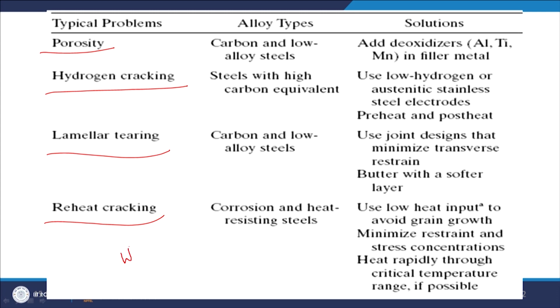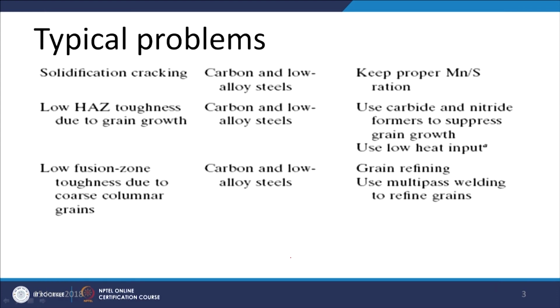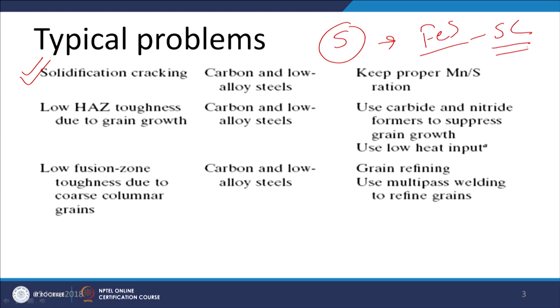In this case, basically the weld joint develops some undesirable phases, and when such a joint is again subjected to higher temperature, either during stress relieving or during service, the high temperature exposure leads to the development of cracks, and that in turn leads to reduced weldability of the metal. Another aspect which governs the weldability of steel is solidification cracking. Most steels have sulfur which during welding forms iron sulfide and increases the tendency for solidification cracking. So, the addition of manganese is used for controlling the solidification cracking tendency.